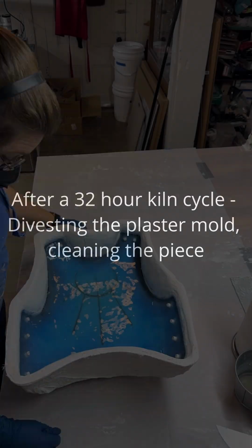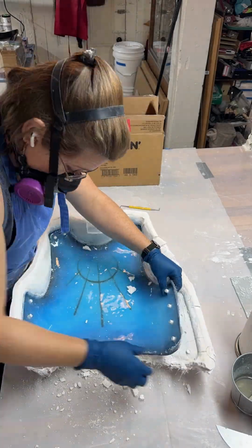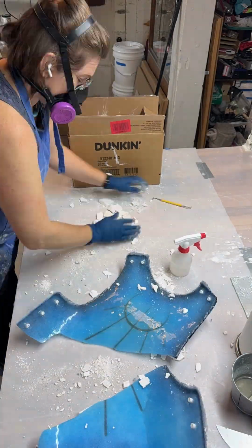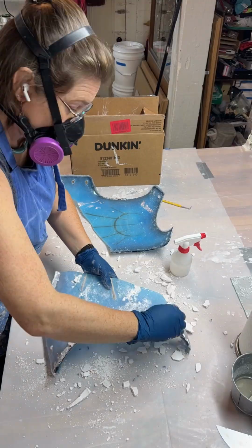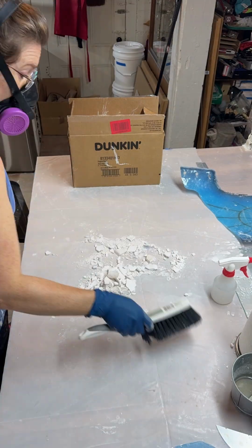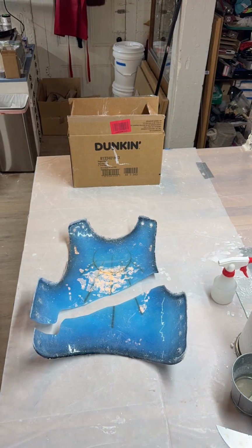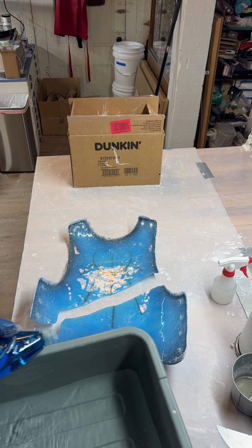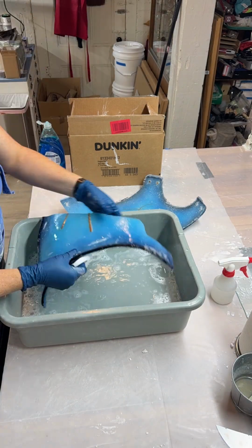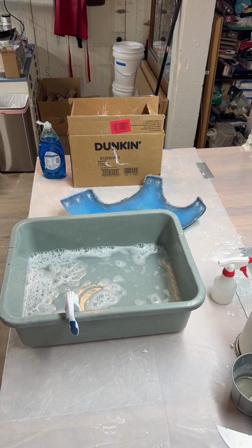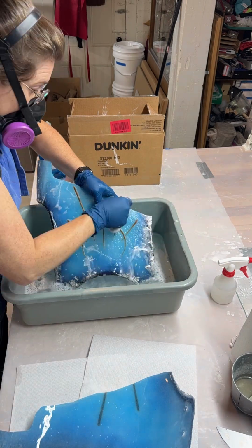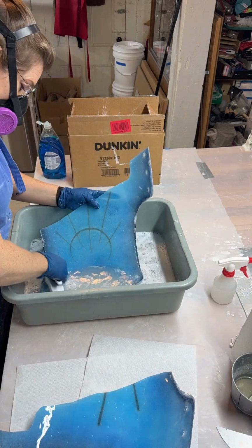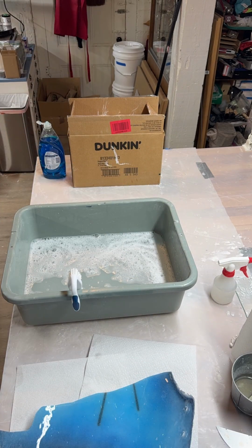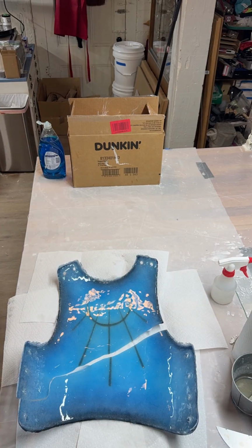Upon opening the kiln, I found a huge crack across the piece, but the only way out is through. I carefully removed the crumbling plaster mold, wearing a respirator and spraying the edges down with water to mitigate the dust. The edges are covered in incredibly sharp little glass spikes, so it's always an adventure to divest and clean. Usually the glass gods get some blood out of this part of the process. The remaining plaster is cleaned from the piece using Dawn dish soap and warm water.